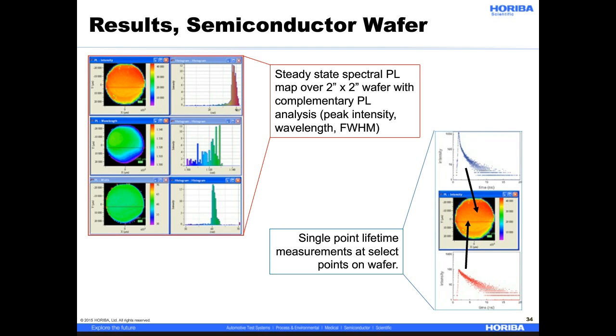As you can see from the differences between the 3 sets of data, different information can be gleaned from analysis of different PL parameters. In addition, changes in band gap or identification of defects or impurities can also be carried out. On the right-hand side of the screen are representative lifetime data that could be recorded from different points on the wafer. With the PL information obtained from the steady-state spectrum, single points on the sample can be identified and lifetime measurements can be carried out. Since both measurements can be made on the same platform, this ensures that the 2 measurements are made on the same spot within the sample.